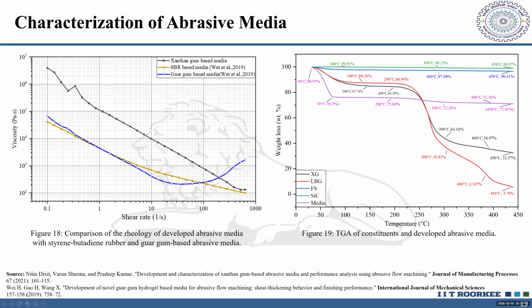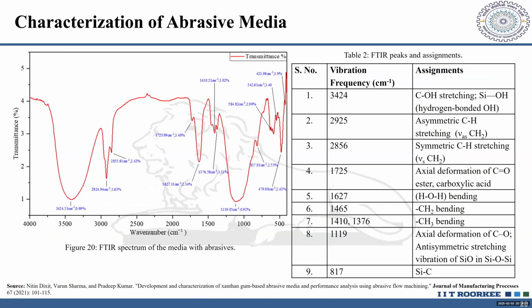Now, from this TGA diagram, you can see that around 74 degrees centigrade, there is a weight reduction of the media. How much weight reduction? From 100% to 76%. So what this signifies is that once you reach a temperature of 74 degrees centigrade, there may be certain weight losses. What I mean by weight losses is that the abrasive holding power would reduce. But ideally, in AFM, the temperature is going to be of the order of 30 to 40 degrees centigrade, at which the weight loss is not that significant. So it says that this particular media that we have developed is good enough, and it could be used for abrasive flow finishing processes, though it is made up of biocompatible and biodegradable media.